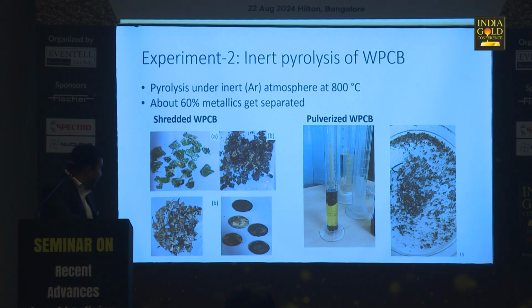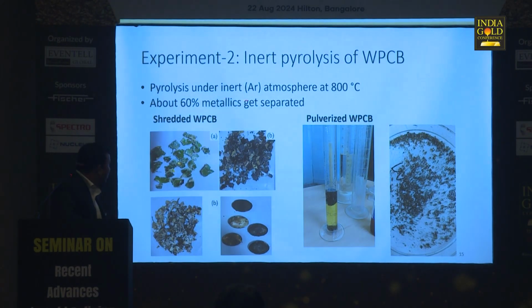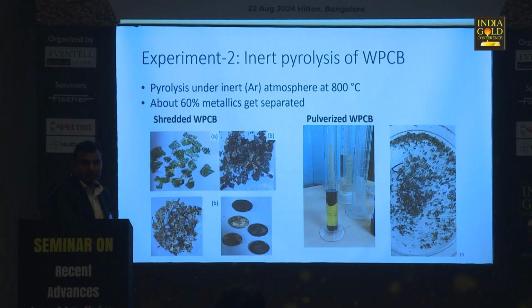However, we learned something more along the process. This is an experiment where we did inert pyrolysis of WPCB, waste printed circuit board, under inert atmosphere in argon, but one can practically do it in nitrogen as well, only at 800 Celsius. Most of these recycling practices are done at least at 1200, 1300 Celsius, but here it is only at 800 Celsius. So once you roast it, you get a mass like this, which is a mixture of some metallics and some non-metallics like your fiberglass, which can be physically separated into these chips or foil-like species, and then you can press it. This is done for the shredded PCB.